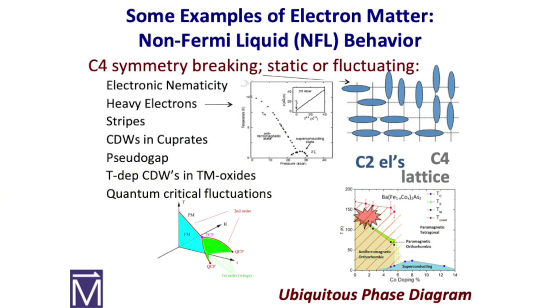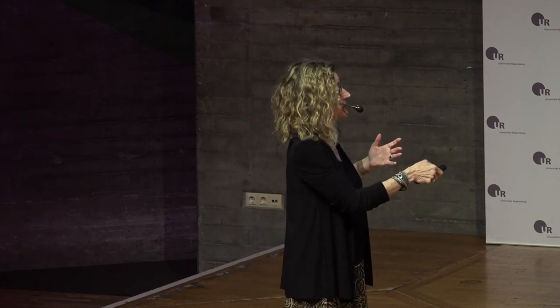And this region here is actually due to electronic nematicity. If you know what a liquid crystal is, the nematic phase is when you have these liquid crystals that kind of line up a little bit, but they don't have translational symmetry like a standard crystal. So what happens in these iron-based superconductors, and we could measure this with our techniques, is that at high temperature